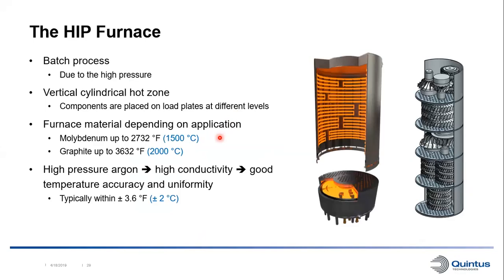Since we have a high pressurized argon in the HIP process, that gives us a very high conductivity of the process gas, and that gives us a very good thermal accuracy and uniformity. So we're typically within plus minus 3.6 Fahrenheit all over the hot zone, in the entire hot zone.